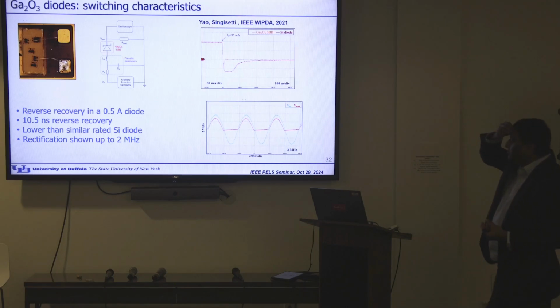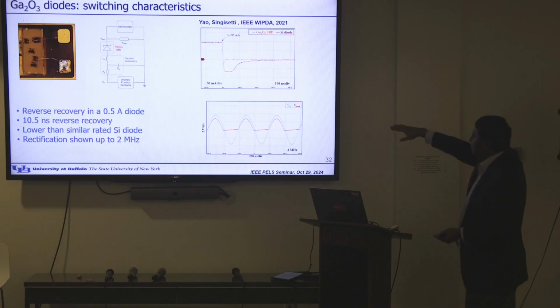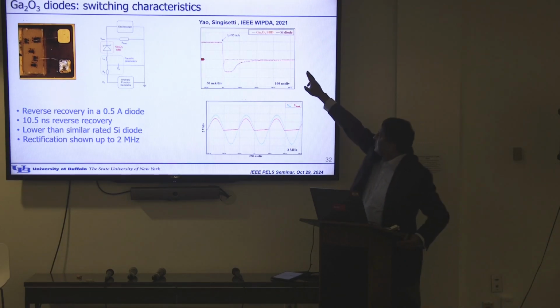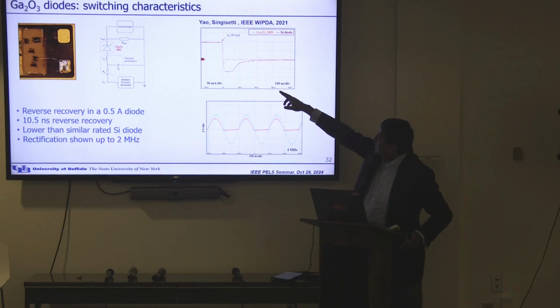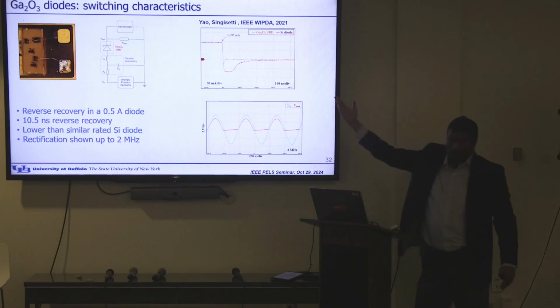And then some quick reverse recovery tests. 500 milliamp device, not very high. This is showing gallium oxide versus silicon. You can see that there is no reverse recovery, right? Because there are no holes here.